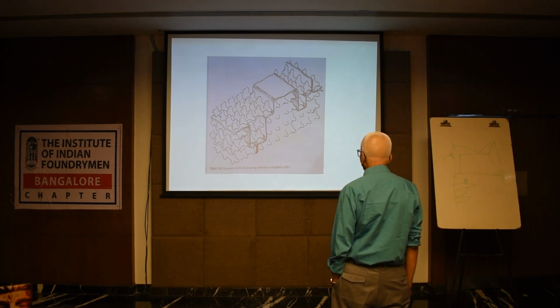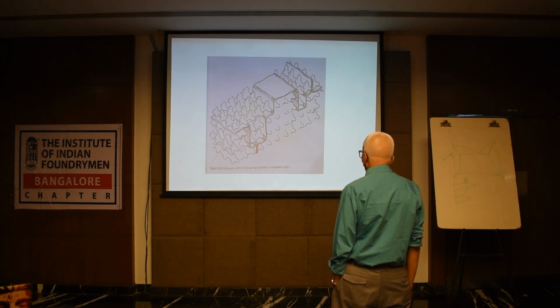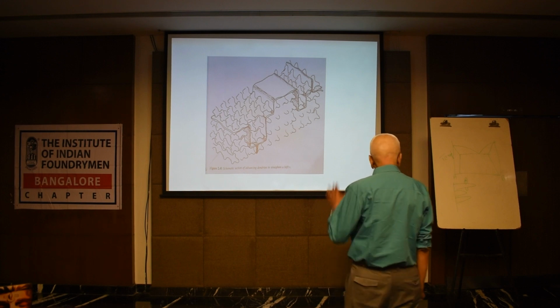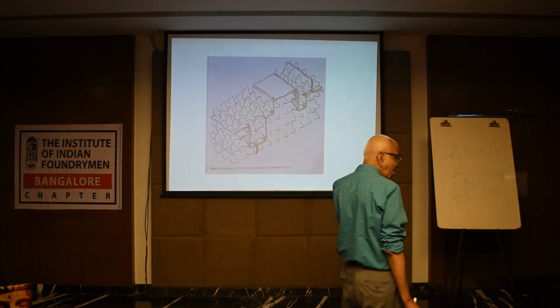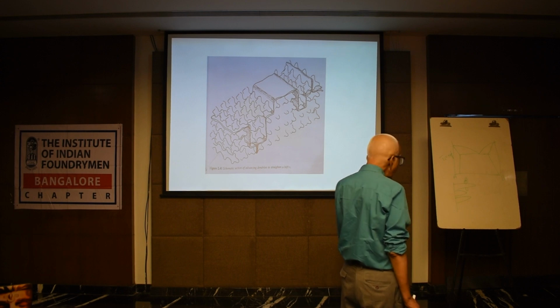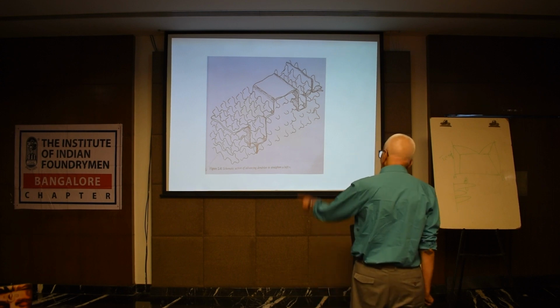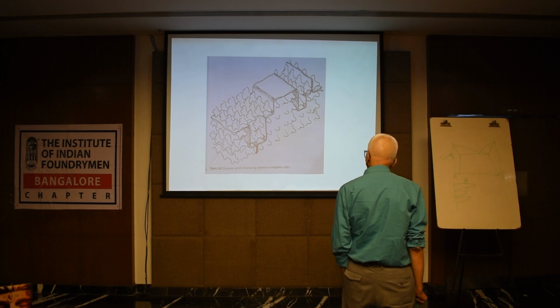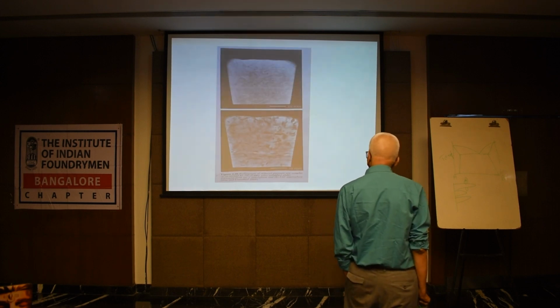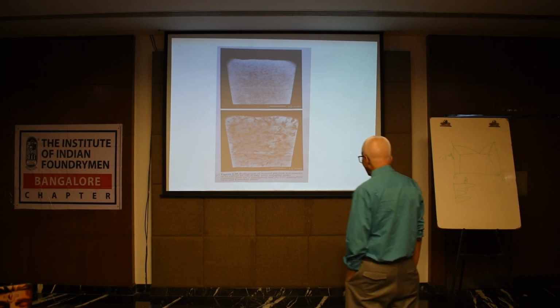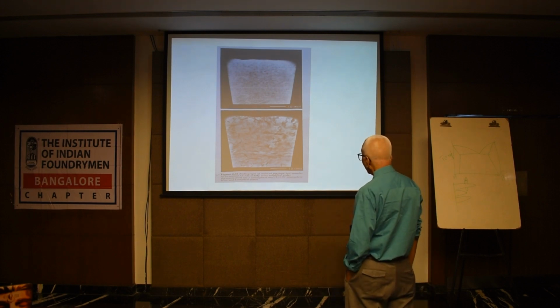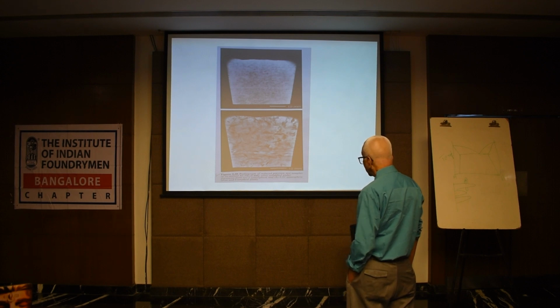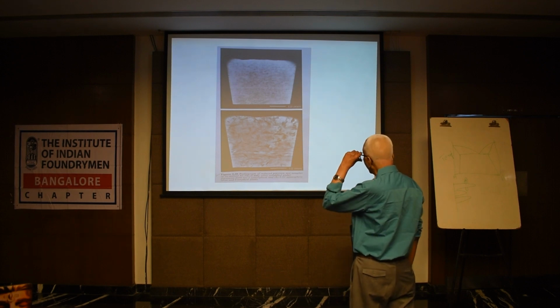You can see a bifilm furled in and entrapped within interdendritic regions, and how, with the dendrites, there's a breakdown of a flat interface into a dendrite. Dendrites try to push the bifilm and straighten the bifilm. Next slide, please. This is a radiograph of a reduced pressure test to check the gas content of aluminum or whatever it is.